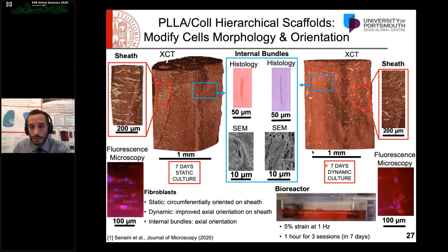What we saw, quite interestingly, was that after dynamic culture, the cells are able to elongate more their shape, not only in the internal bundles where the nanofibers are aligned, but also on the external membrane, which is basically randomly arranged. You can see this from different images we acquired with different techniques, such as high-resolution X-ray tomography, SEM images, histology, and fluorescent microscopy.